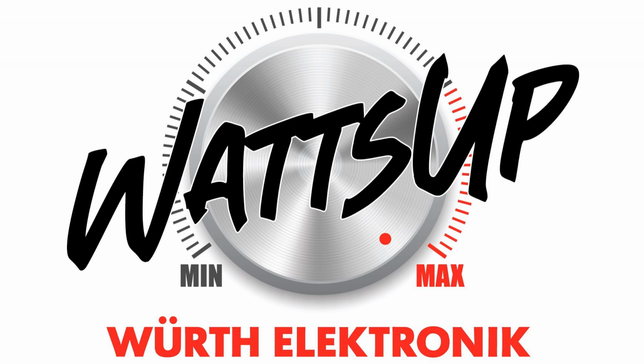Würth Elektronik WE-TGF is a silicone-based elastomeric gap filler, and this is one of the most popular gap filling solutions because of its wide range of thicknesses and its performance. The gap pad is tacky by nature, so it's going to stay in place during assembly until the final compression. Optimal performance is reached when the pad is compressed between 10 and 30% of its thickness.